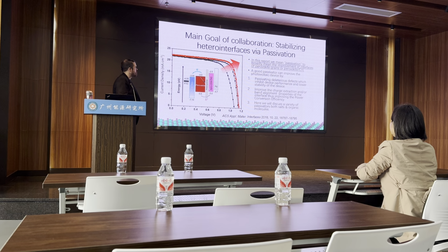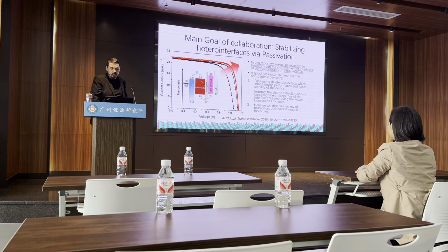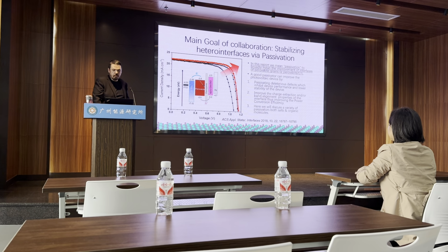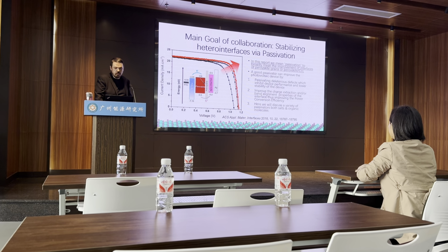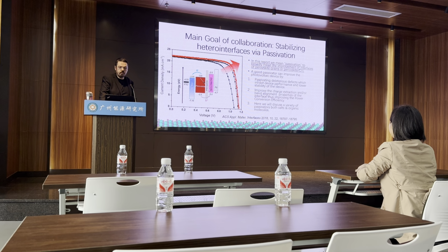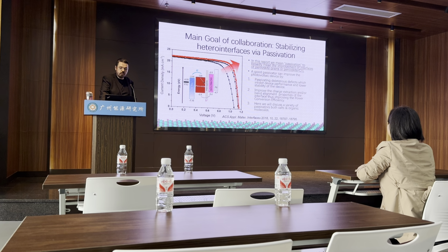When we say good passivator, we mean that it can improve the photovoltaic efficiency and the stability of the device by first passivating the deleterious defects, which inhibit device performance and just degrade it in general. Improve charge extraction and/or the band alignment. So this will directly improve the power conversion efficiency, but it's actually quite a difficult thing to calculate. And here we will discuss both basically salts and organic molecules or organic salts.